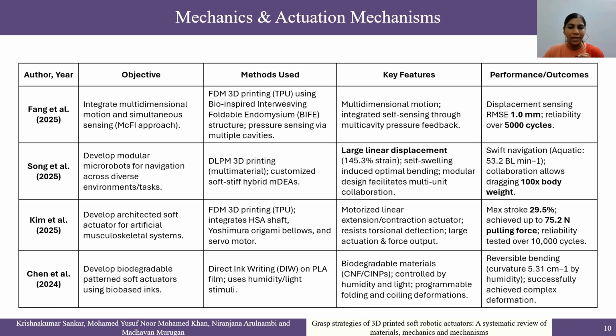Kim et al. used a sophisticated motorized actuator with HSA shafts and origami bellows, which was able to achieve 29.5% maximum stroke and 75.2 newtons of pulling force with 10,000 cycle durability as seen before. Chen et al.'s biodegradable design used humidity and light stimuli for programming deformations with 5.31 centimeter inverse bending curvature.